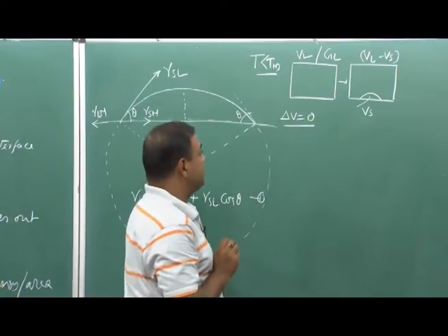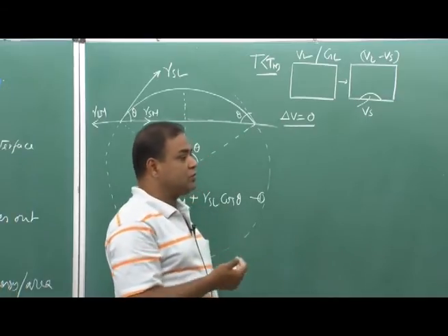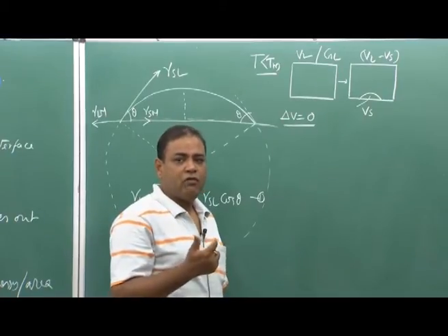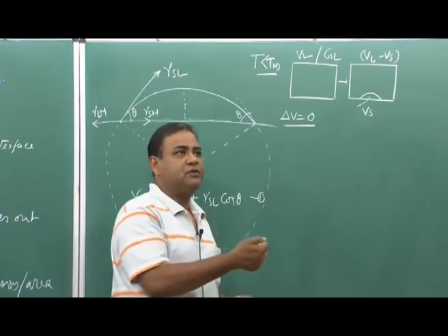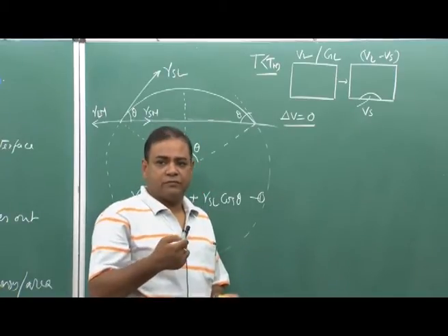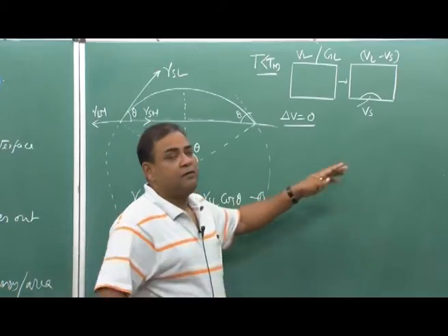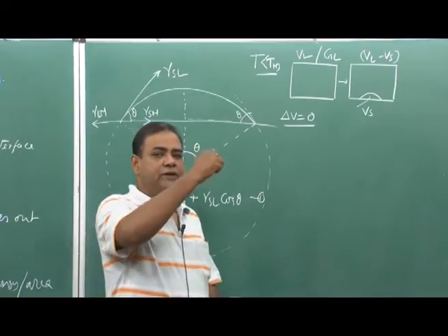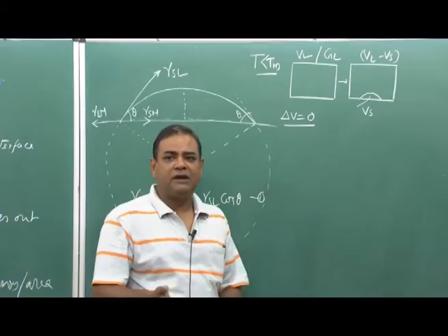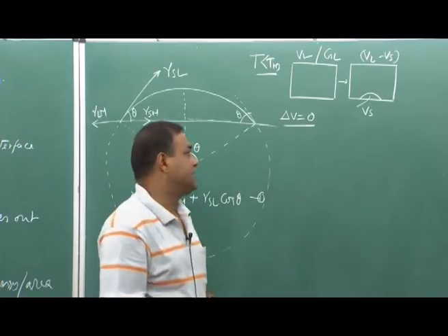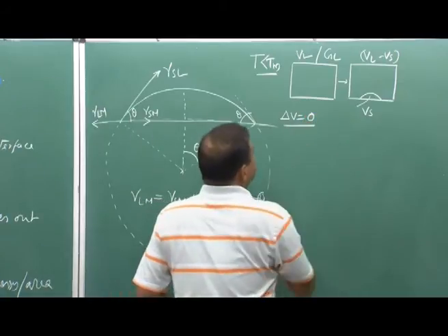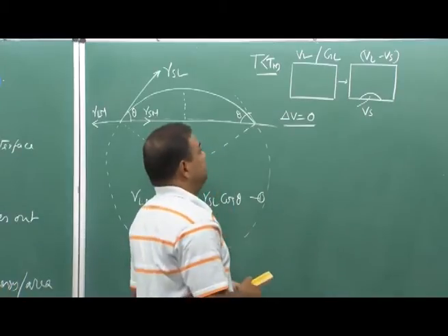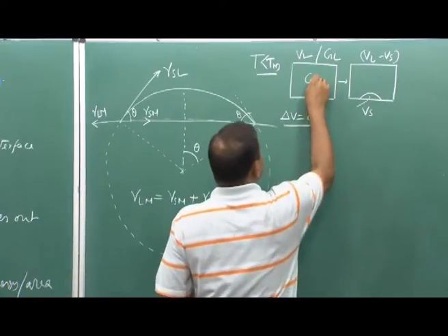Though it does not happen, whenever a solid to liquid or liquid to solid transformation happens, there will be a definite volume change. For example, in case of water, the volume increases during solidification, that means liquid water to solid ice. But in case of liquid metal, for example aluminum or iron, when solid forms, the volume decreases. That is what gives you the sinkage problem in casting. We are taking this assumption to have a very easy treatment of this problem.